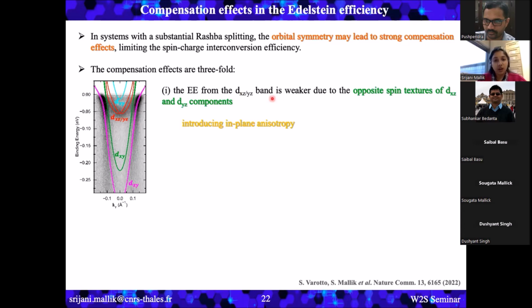So the KTaO is cubic. So this means it's isotropic in nature, but maybe we predict that we can solve this problem by introducing some in-plane anisotropy so that it's not anymore 50%, 50% of dxz, dyz, and then we can really get a very high spin Edelstein effect from this band pair.